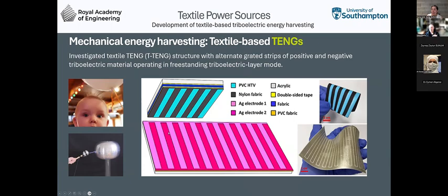So in this case, we've designed a textile triboelectric harvester that has two triboelectric materials, a positive and a negative: PVC fabric and nylon fabric. This slides backwards and forwards along this silver electrode. As it slides, you get a charge being transferred from the positive to the negative material, and that builds up an electric field, and you get voltage pulses as it moves across these electrodes. By having both positive and negative materials, you get positive and negative voltages that combine to double the amplitude of the output.